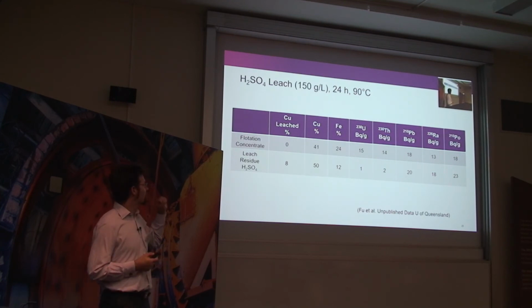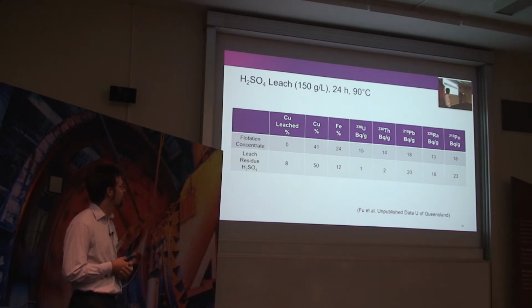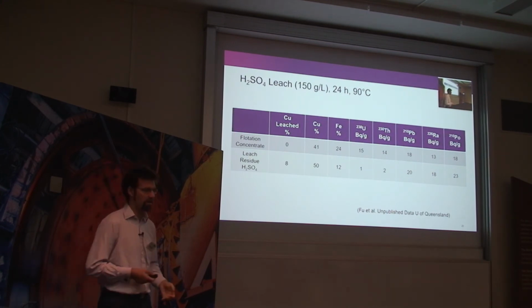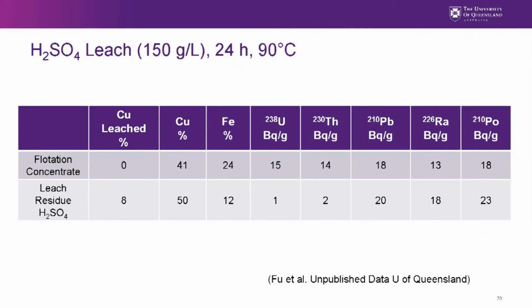So here's another table showing the result of a 90 degrees sulfuric acid leach of a flotation concentrate in 150 grams per liter, this time for 24 hours, a little bit longer. We're aiming to dissolve a lot of the gangue minerals in this case. So the initial flotation concentrate was 41% copper, 24% iron. Under these conditions, we could knock the iron down by about half. We leached about 8% of the copper here, but the grade still went up to 50%. The initial RNs coming in were around 13 to 18 Bq per gram, and the sulfuric acid leach even at 90 degrees was pretty effective at separating uranium and thorium, but not lead, not radium, not polonium.